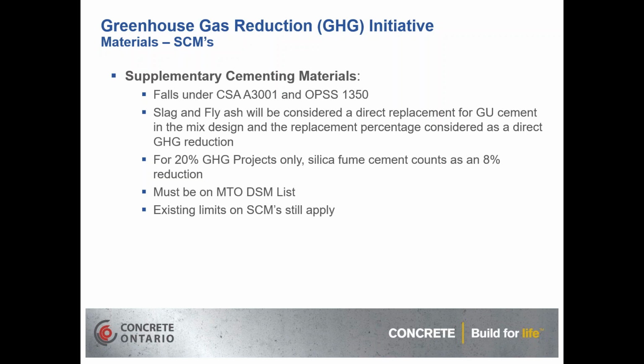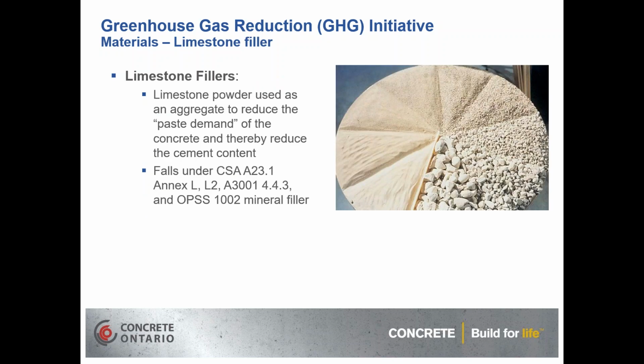Now, for the 20% greenhouse gas projects only, the silica fume cement is going to be considered as having an 8% reduction, because typically the silica fume cements are somewhere around 8.5% replacement. Again, these materials, if you want to use them, they must be on the MTO designated source list or designated source materials listing. And those limits that they have on the SCMs, the 10%, the 25% for the fly ash and the slag, those still apply.